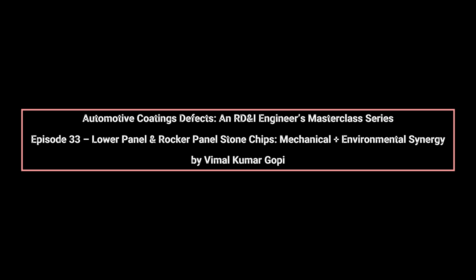Film build plays a decisive role in stone chip resistance. OEM specifications deliberately increase total film thickness on rocker panels compared to upper body surfaces. However, achieving uniform thickness is difficult due to geometry, spray angle limitations, and line speed constraints. Thin spots become preferential chip initiation sites. Conversely, excessive build increases internal stress and brittleness, which can worsen chipping severity under repeated impact.